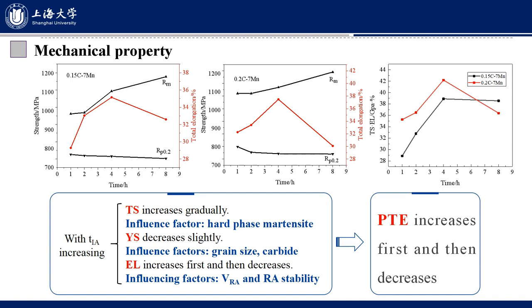Influencing factors include the volume fraction of retained austenite and its stability. Finally, we know that the product of tensile strength and elongation increases first and then decreases, and the best condition for intercritical annealing time is 4 hours.